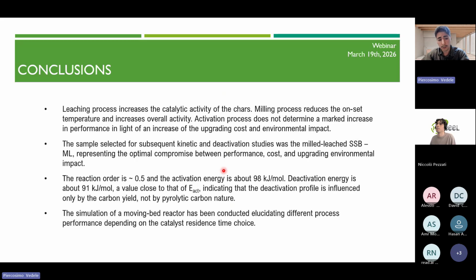From the kinetic tests, we observe a reaction order and an activation energy which are quite in agreement with those of the literature. That indicates that the deactivation profile is influenced only by the carbon yield, the amount of carbon deposited, and not by the pyrolytic nature of the carbon deposited.